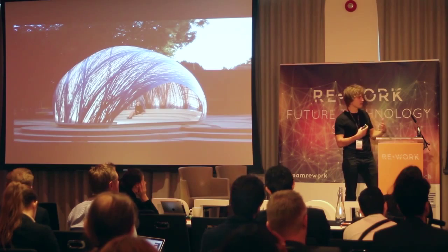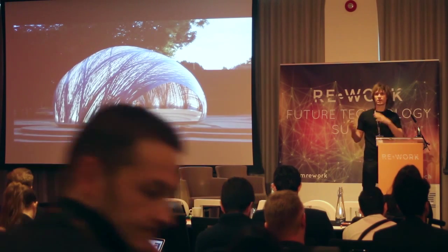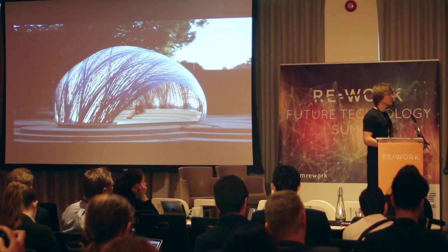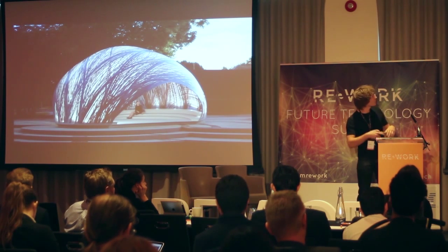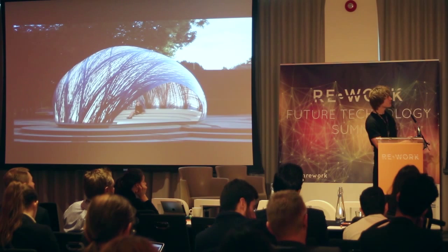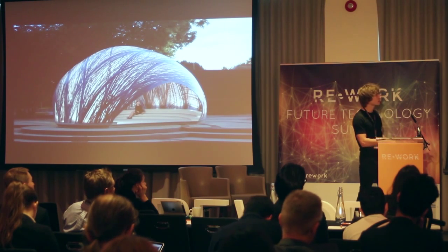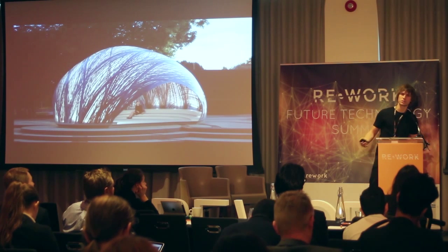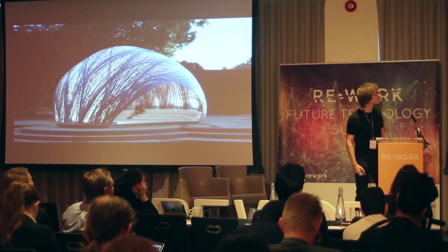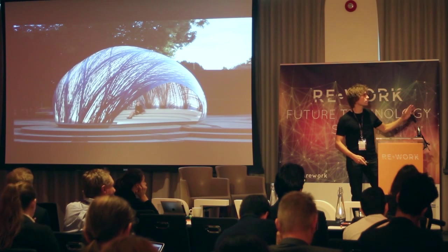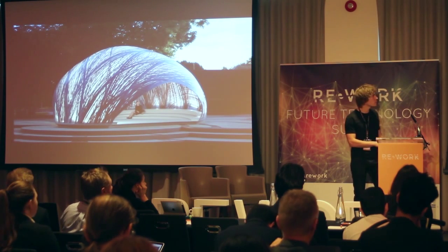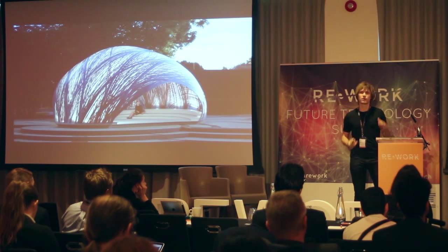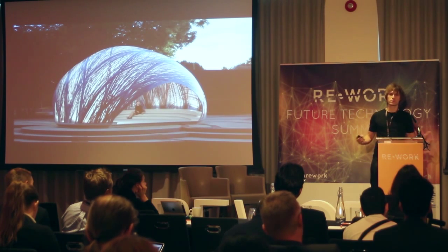What does it mean in the end for architecture? It's not, I mentioned that before, not just a technical challenge that we managed to resolve, but it really allows ourselves to, for example, here we went one step further. The formwork is now an embedded facade system, for example, as well. The ETFE is a building-grade material that's used in stadiums. So we have a very lightweight construction. So the whole thing weighs 250 kilograms. It's around 50 square meters. So we have a construction weight of 5 kilograms per square meter.